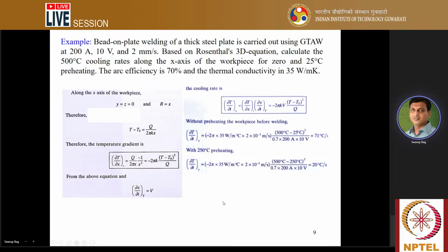So we can see that if there is preheating, there is a decrement. That means the cooling rate actually decreases. So that is the solution. This kind of inference, or simple calculation, we can perform using the Rosenthal 3D equation. Although nowadays numerical solutions are also available, where we can see more accurate temperature distribution results, using finite element based numerical techniques, the analytical solution is still valid to get a very quick but approximate solution of a welding problem. I think that's all for this particular case.